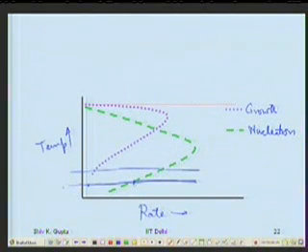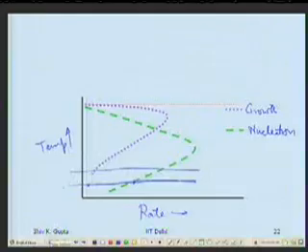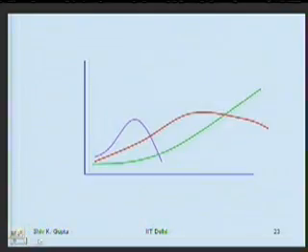It's going towards equilibrium, but the rate of the process is so slow and nucleation is at such a slow rate, I get very fine precipitate particles, but they are unable to grow. So I get fine precipitate. As time progresses, I get more and more precipitate, meaning the interparticle spacing decreases more and more, so the strength and hardness increase more and more with time. This process is also called age hardening. As the time the alloy is kept at room temperature increases, its hardness increases. Right? That's what it is.